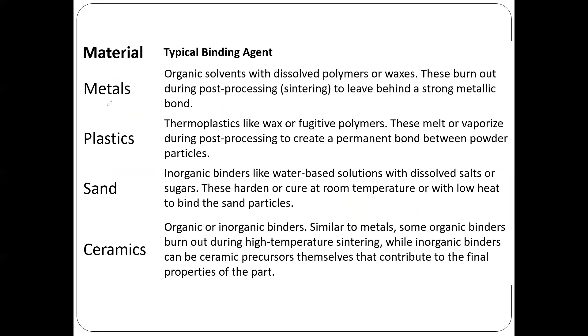These binders could be, if we're dealing with metals, generally organic solvents with dissolved polymers or waxes. These are generally polymeric or wax materials which burn out during the post-processing sintering to leave behind a strong metal. They generally burn when you put them through the sintering process and only powder particles will sinter together.